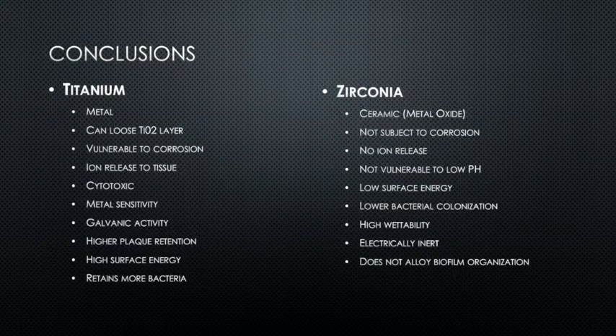So, before we go to clinical cases, based on what we talked about: metal, ceramic, can lose a titanium oxide layer, not subjected to corrosion, vulnerable to corrosion, no ion release, galvanic activity, not electrically charged, low bacterial colonization, higher bacteria, higher plaque, high surface energy, low surface energy. When I look at all these factors, I have no choice but to call zirconia biocompatible and titanium biotolerated.